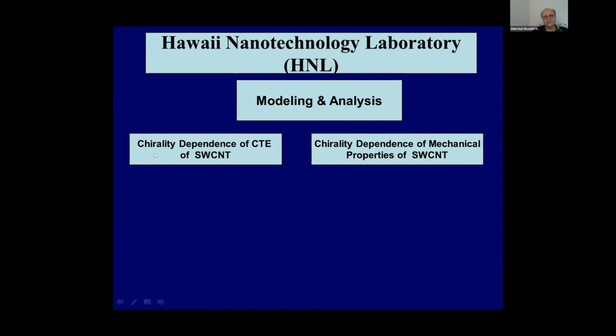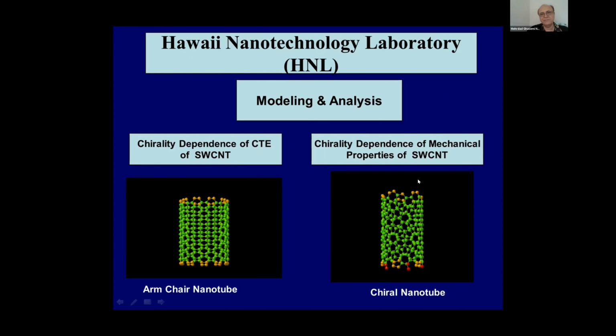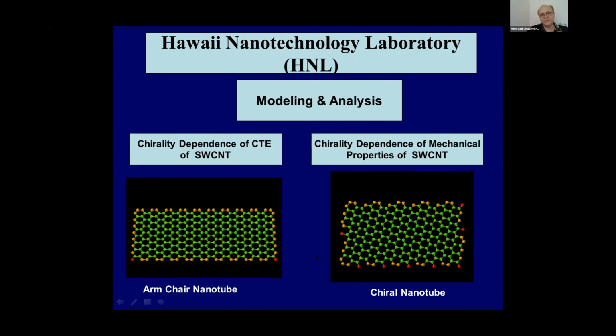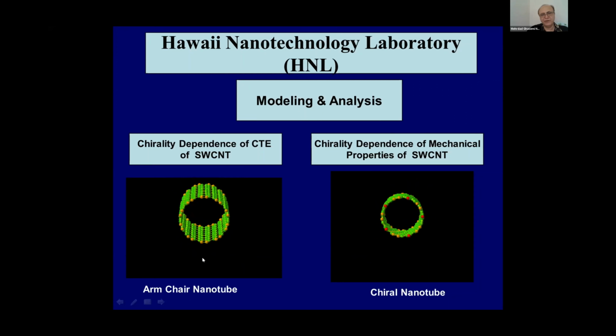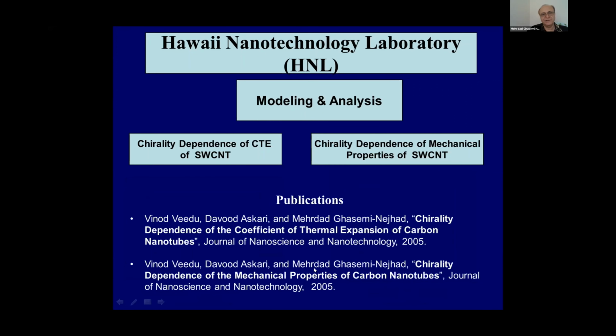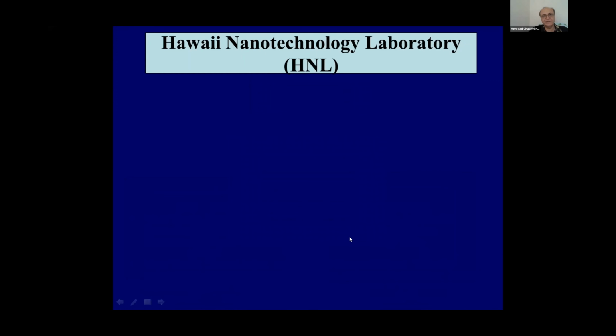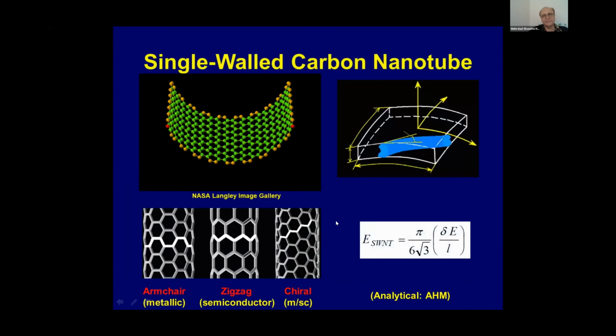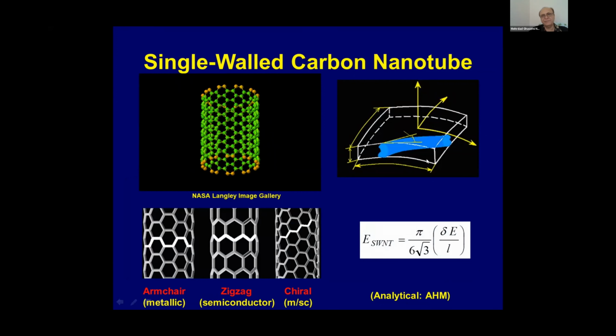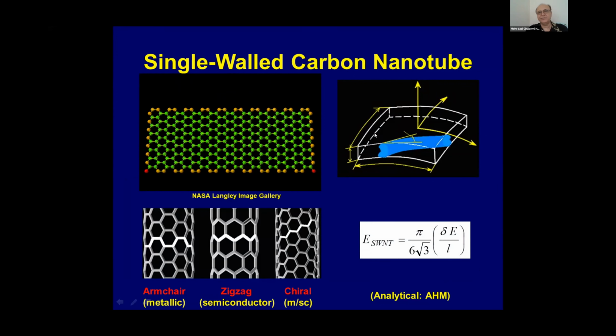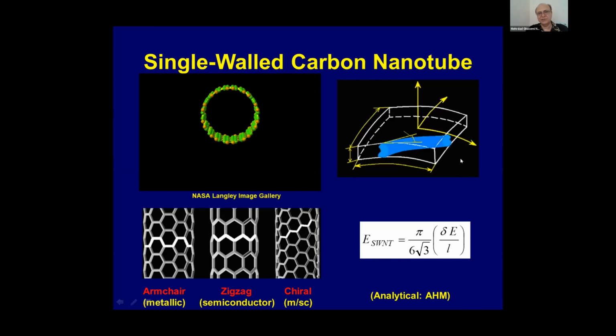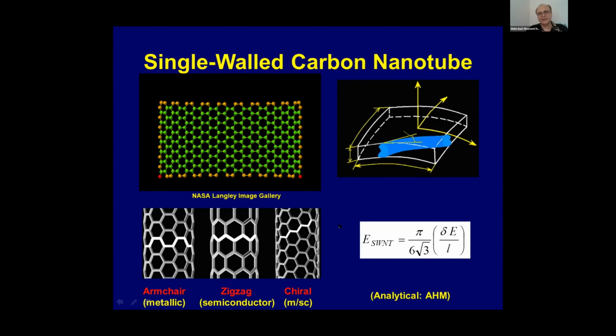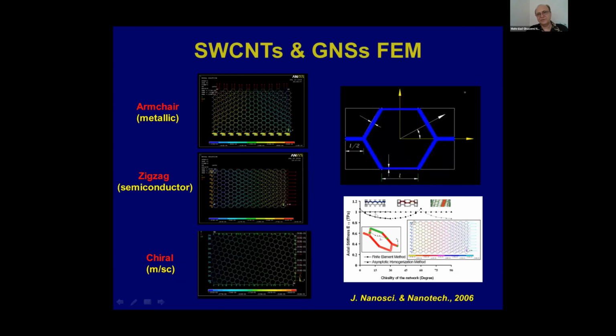So I said we had a paper on chirality dependence of CTE, coefficient of thermal expansion, for single wall carbon nanotube, and also chirality dependence of mechanical properties. Here we show different organizations of the carbon nanotube, armchair, zigzag, chiral. So those are the two papers that I mentioned, and also some applications. We modeled the effective modulus of the single wall carbon nanotube using asymptotic homogenization. This is an analytical solution. And then we compared that with finite element analysis for different chiralities. And then the result was very close.